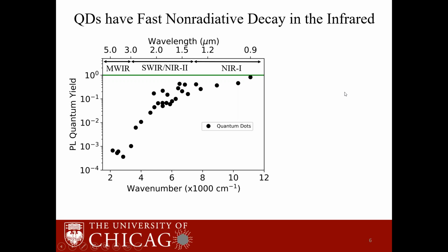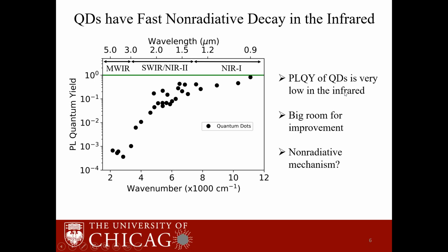But as you go into longer wavelengths, like the shortwave infrared and the midwave infrared, the quantum yield drops really quickly. Especially at 5 microns, the quantum yield is just a few times 10 to the minus 4. So this tells us that there is a lot that can be done to improve the properties of quantum dots in these wavelength regions. And this also brings about the question, what is the reason for this exponentially decreasing trend of the quantum yield? And can we do something to overcome this?